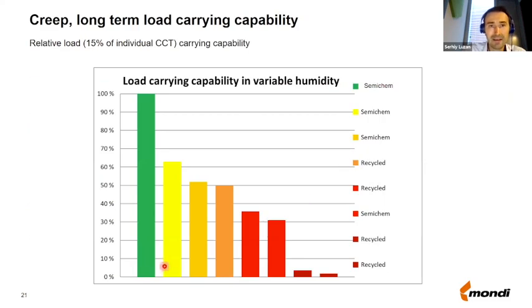So here you have a comparative analysis percentage-wise, comparing different types of semi-chemical flutings and recycled flutings. So the higher the bar is, the longer the paper can hold the load in the humid conditions. And the lower the bar is, the shorter the time is. And you see that on the left-hand side, you have mainly semi-chemical flutings. On the right-hand side, you have mainly recycled flutings. And you see that the differences actually are very large. So the differences are very big between the flutings made from different types of fibers.